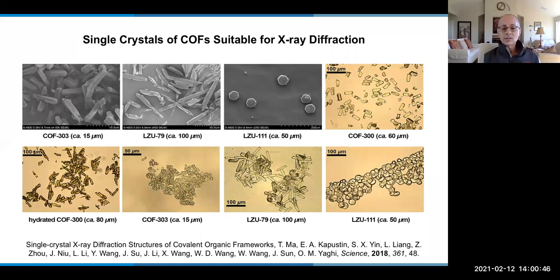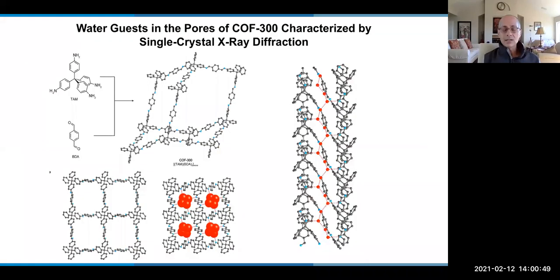And the question is, did we get the right structures from the powder? And the answer is yes, we got the right structure, but now we know exactly the bond lengths and angles. Also, in the powder structures, we didn't get what's inside a structure. But now with single crystal, we can say that with COF-300, there is a chain of water molecules that we did not refine in the powder, but can observe in the single crystal X-ray diffraction. So this is the power of single crystal X-ray diffraction, that it gives you as much information as possible about the environment in the pore, as well as the framework.